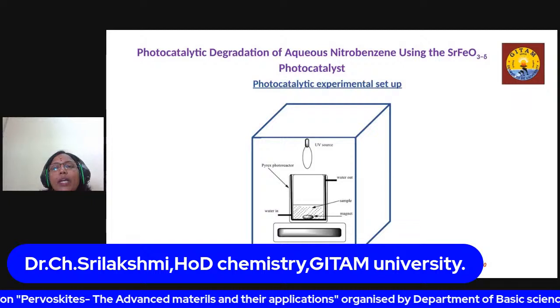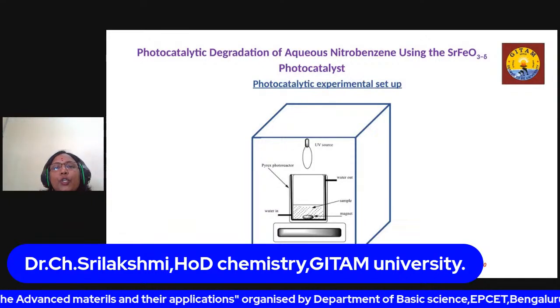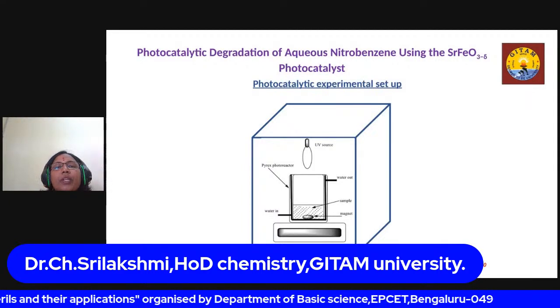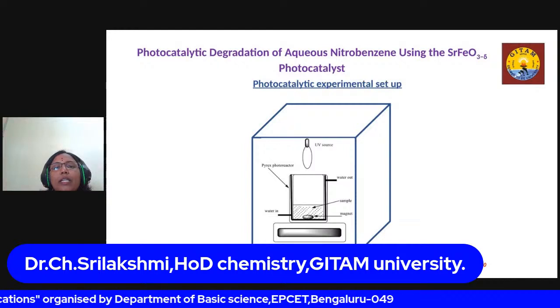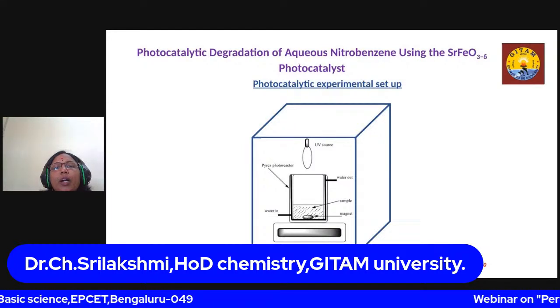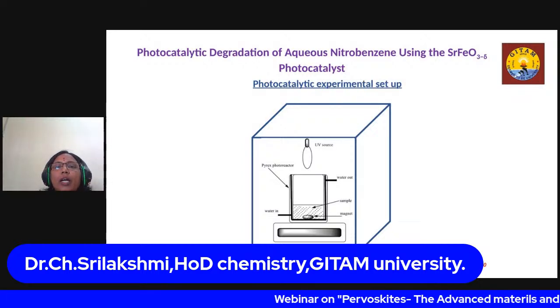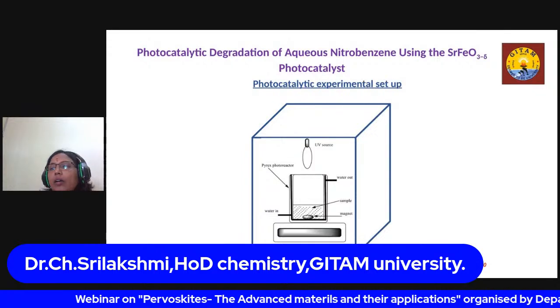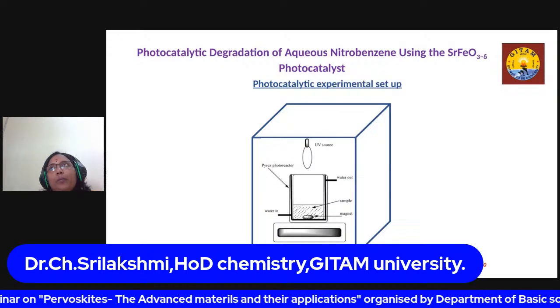It is a wooden case fitted with UV light, and this is the glass reactor. Both of these, which is not shown here, are encased in a quartz tube in order to circulate water through them to avoid any thermal decomposition. So all the photocatalytic experiments are conducted at room temperature.